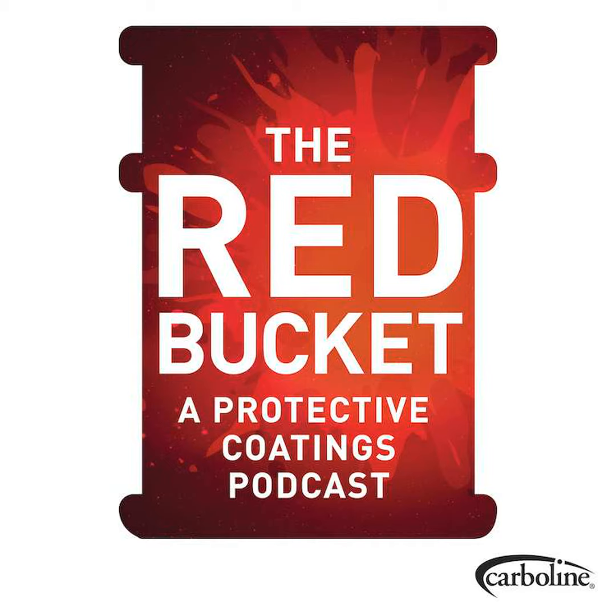The blending is what I see is how you want the coating to, you don't want any sharp edges, because the coating tends to pull away during the curing process. So you have very minimal film thickness in those sharp edges. So mechanically, you take a grinder and blend those corrosion areas, not have any bridging, where you'll have a discontinuity.